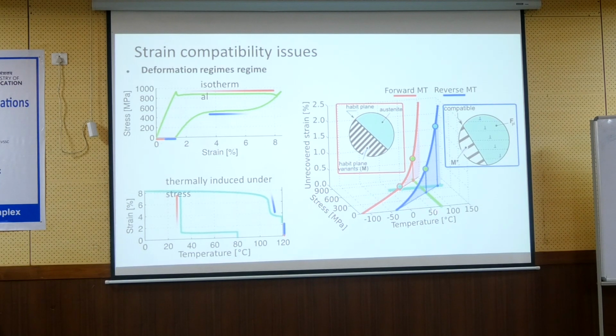It's better not to speak about high temperatures or high stresses separately because they are related. The stresses and temperatures at which transformation proceeds are related by this Clausius-Clapeyron equation. So you will find out how quickly it increases, and this increase basically kills your superelastic or actuation applicability. So to be on the safe side, you have to be somewhere here. And so the problem for scientists is to find out the origin of this phenomenon.